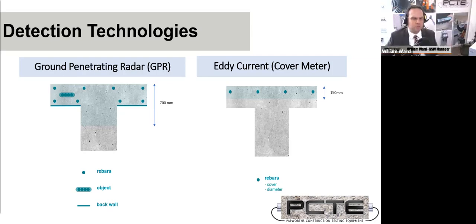Ground penetrating radar is a scanning technology. It has the ability to locate multiple layers of embedded steel in a structure. It's also sensitive to non-metallic targets, so it could find conduits or other targets inside the reinforcing steel, and will determine backwall or thickness within the bounds of around a 700 millimeter maximum depth.